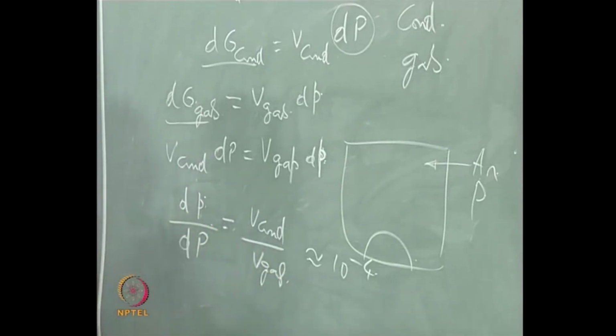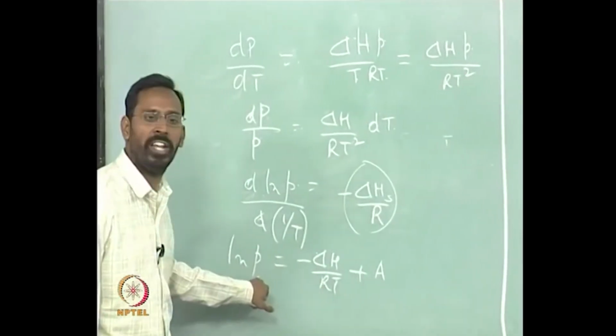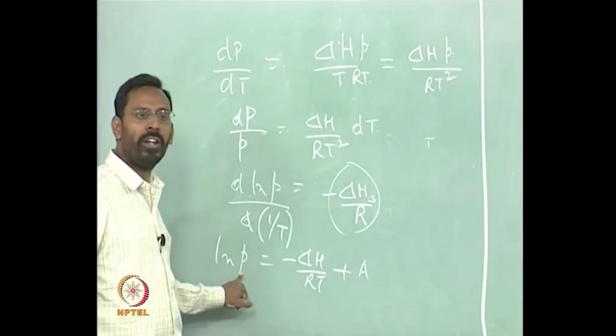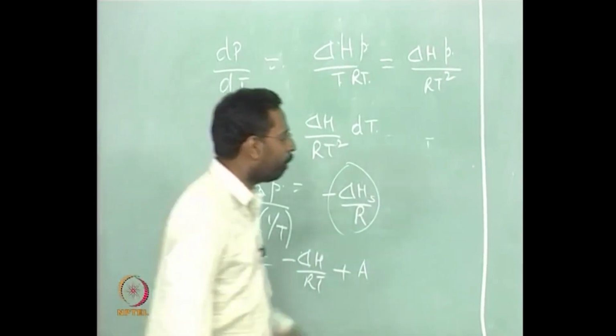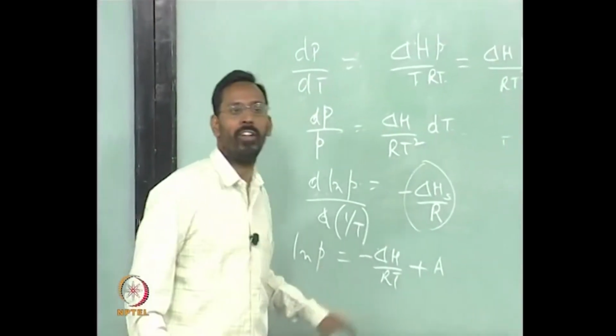So this is something which you have to see, whereas if you look at the previous thing, the change of partial pressure with temperature is very, very significant. You can see here, as we have also written down earlier, P is exponentially related to temperature, while the partial pressure is not related significantly to the pressure that is there. So these are the two aspects one has to remember whenever we are talking of gases coming out of solids, and how temperature and pressure, which are the two important state variables, influence the formation of gases from a solid.